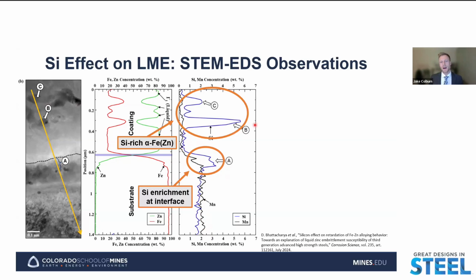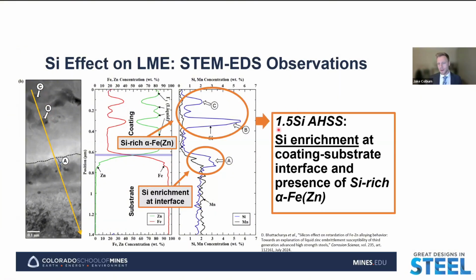But we also see the presence of these silicon-rich alpha iron zinc islands. And so this alpha iron zinc phase is essentially a BCC iron phase that has appreciable solubility for zinc, as well as also having a decent solubility for silicon. And so we see these little islands here, pointed out by C and B over here, of this alpha phase. And so again, for the high silicon containing steel tested at 700 degrees C, we see this silicon enrichment at the interface as well as the presence of these iron alpha zinc phases.